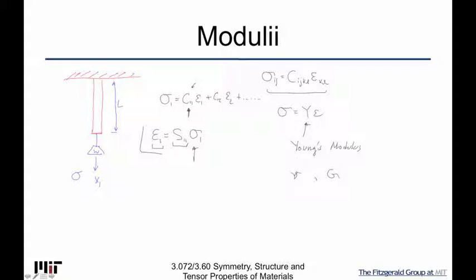Now, what people have done is they've realized that, and then they express the biaxial modulus in terms of Young's modulus and Poisson's ratio, which is even more confusing because you're using moduli that are inherently related to uniaxial experiment. And my preference is that any time that you're not in this case, you should actually go back to the CIJKL. It's a very common mistake.